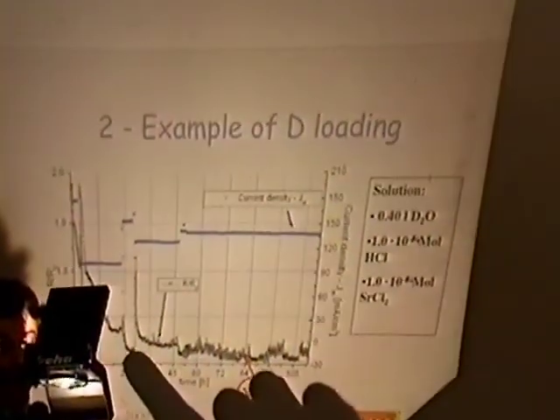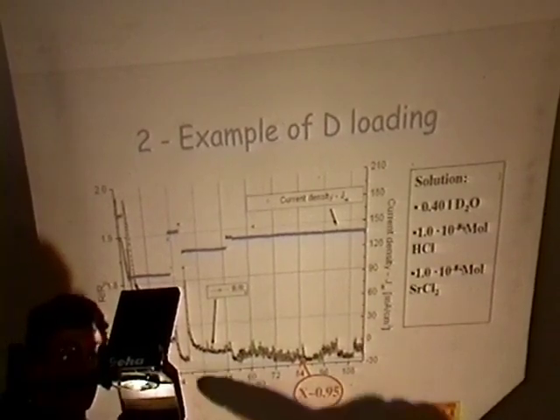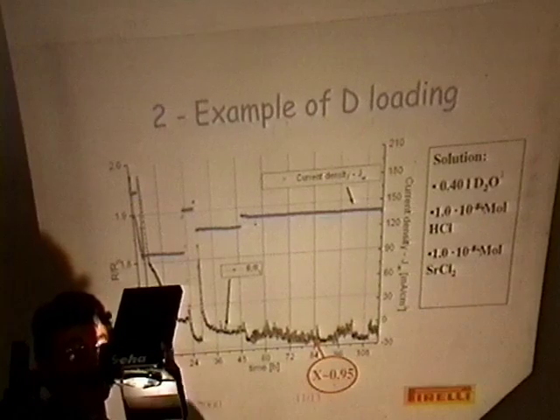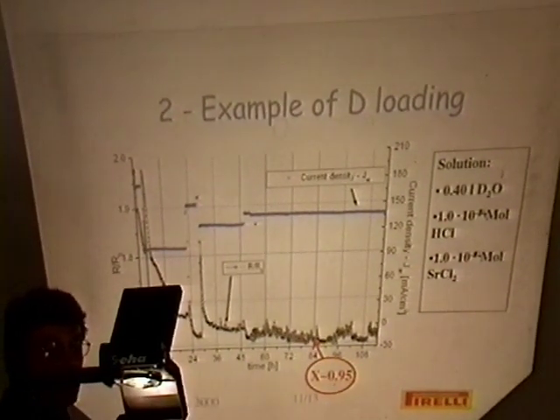Do you have experience in deloading and reloading these? Is there any hysteresis or what happens? I tried several times to load in different cycles with deuterium, and what I can see is that usually the second and third loading is faster than the first one, and we can reach the previous values quite faster. In this example, at this point we deload by turning off the current, and the second loading was quite faster than the first one. It takes only about a quarter of the time.